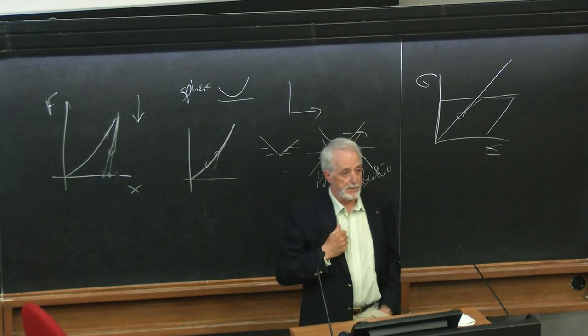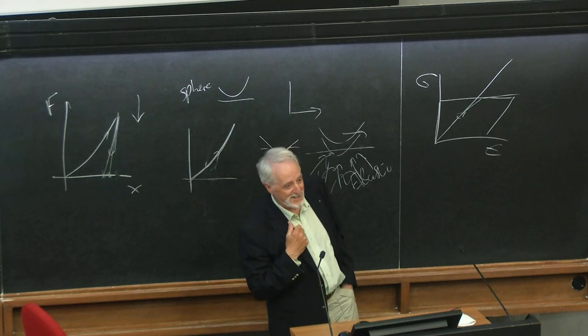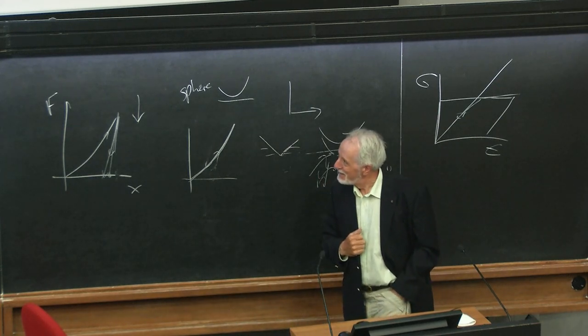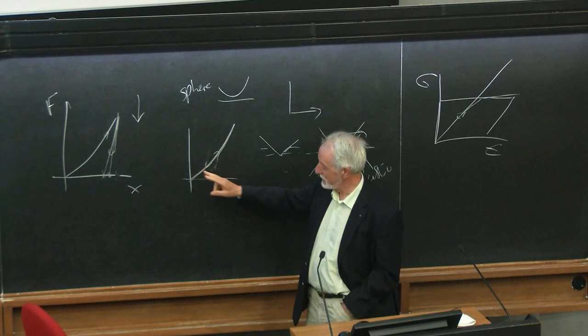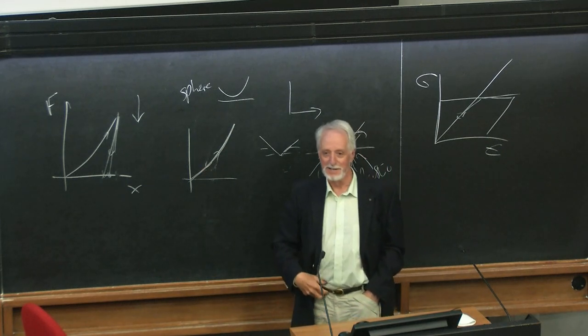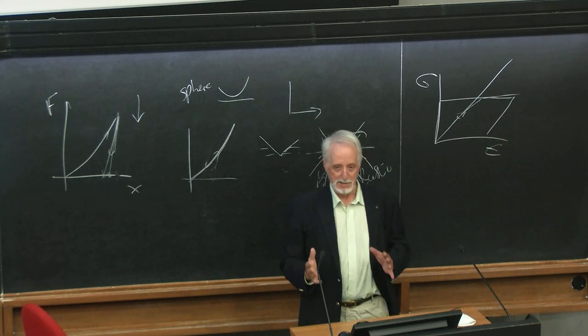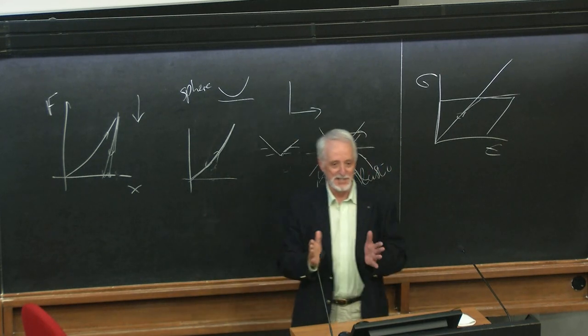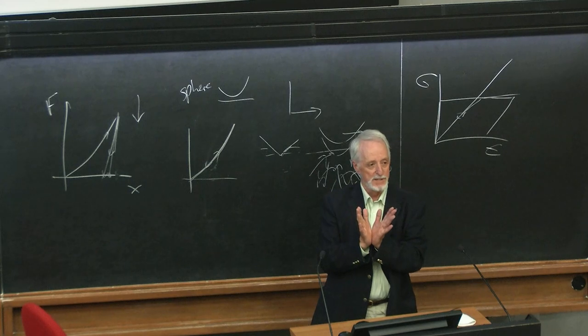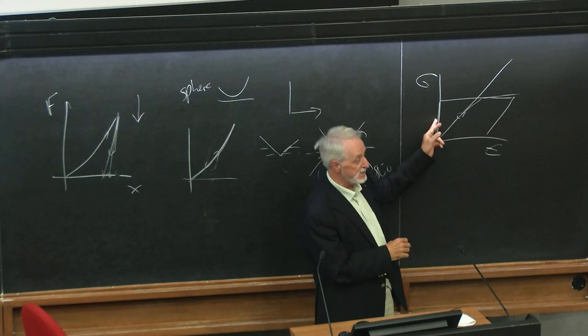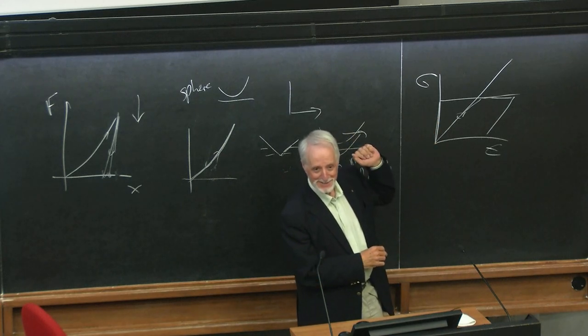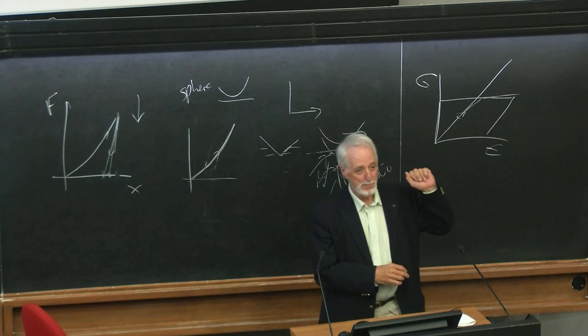I would be dishonest if I were to tell you this problem is entirely solved. Right? There are some rather strange things happening when you get very small loads here, which, again, is what you'd expect in nanoscale work. One of which is that, and I might as well tell you this, when you use very small shifts, the process is laterally elastic too. If you're a person into plasticity, this is bad news. Right? It shouldn't happen, but it does.